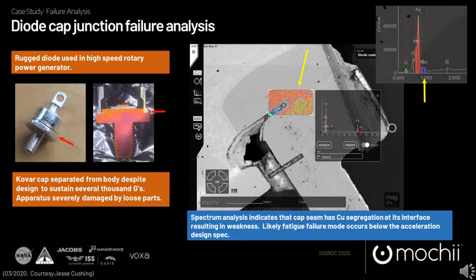In this investigation, a rugged diode used in a high-speed rotary power generator kept failing, throwing off its Kovar cap under a few thousand Gs and damaging the apparatus spinning at very high RPMs. The investigation using Mochii's spectrum imaging feature indicated copper concentrated at the interface seam, resulting in weakness despite the strong housing components. Likely failure mode was fatigue exacerbated by a segregation of softer metals to the seam.